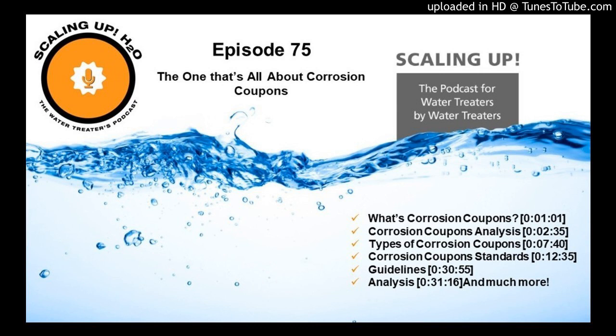We call that process passivation. If we put a brand new raw corrosion coupon in that system, it does not have the benefit of having that passive coating, that passivation. So we are going to get a more rapid corrosion rate in the first couple of days of that coupon. Now, if we only have that coupon in there for 30 days, a lot of those 30 days is going to be indicative of that higher corrosion rate. So if you are only using 30-day coupons, expect your corrosion rates to be a little bit higher than they actually are in the system.